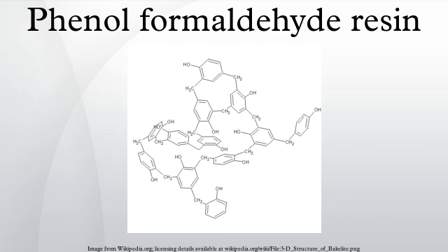Resols: base-catalyzed phenol formaldehyde resins are made with a formaldehyde to phenol ratio of greater than 1. These resins are called resols. Phenol, formaldehyde, water and catalyst are mixed in the desired amount, depending on the resin to be formed, and are then heated. The first part of the reaction, at around 70 degrees Celsius, forms a thick reddish-brown tacky material, which is rich in hydroxymethyl and benzylic ether groups.